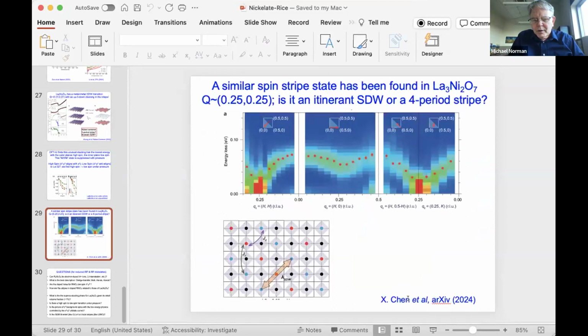And so you can see in this paper, the black things are magnetic, so you can sort of think of them like holes, and then you have the red and blue. This looks like a standard charged spin density wave stripe like you get in cuprates, but they've looked at other models where you have up, up, down, down, which is a pure spin density wave with no charge component to it. Yeah, my suspicion is that you have both charge and spin.